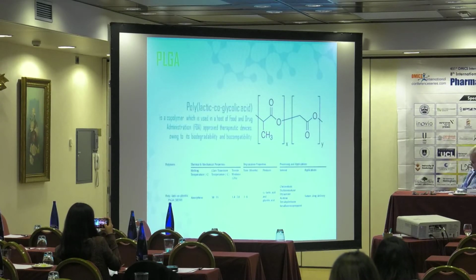It's approved by the FDA. In our case, we are going to use PLGA, and we use it because of the degradation time that PLGA exhibits. As you can see in the chart, we have 3 to 6 months of degradation time, but you should take into account that the chart refers to pellets of PLGA. So if we have a nanoparticulated system, this degradation time will change, in order to achieve practical degradation times for drug delivery, to modulate the release of our active, or the goal that we wanted to reach.